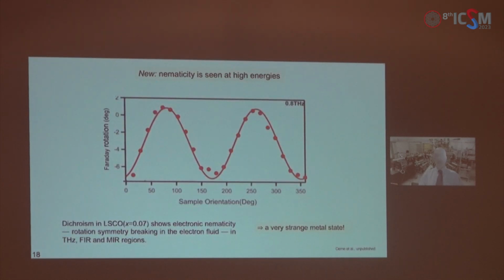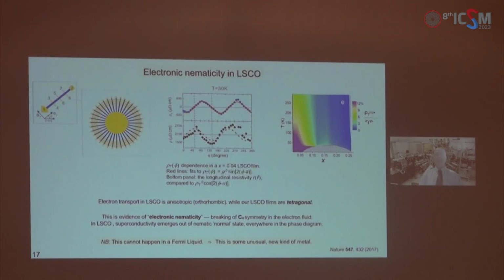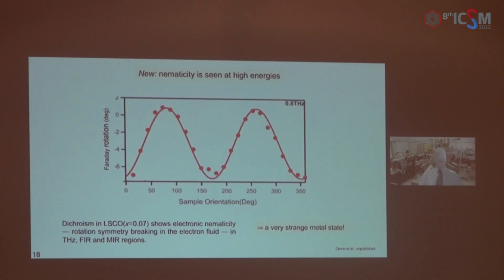Now, one of the most positive aspects here is that we see this everywhere in the phase diagram, except for the extreme overdoping, and all the way up to room temperature. Now, this means that this order is very strong and robust. And we have tested this by some new experiments that actually corroborate this.